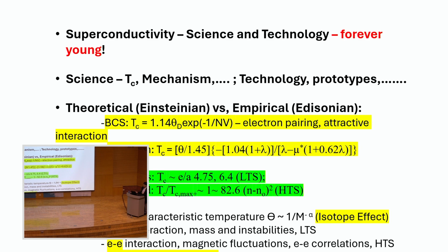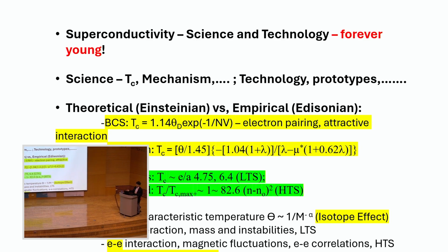It turns out that the theory predicts the Tc correctly. What they did not tell you is that mu star was an adjusted parameter in this case. You cannot accurately calculate mu star, so they put in a number, say it's a reasonable number, and they get the result. So even for these hydrides, they consider them electron-phonon interaction superconductors, like hydrogen sulfide and so on.